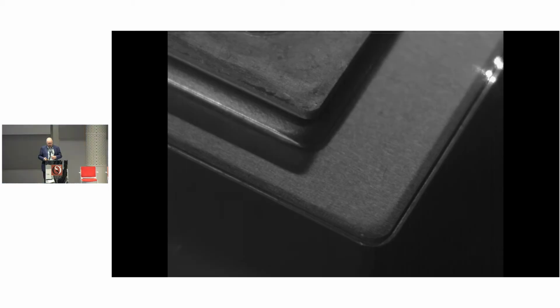And this looks like this. You have the scan line. This is 160 times slower than in reality. You see the pilot laser that would indicate the weld laser, and we just follow exactly the path around the battery in order to ensure the right position of the beam on the part.